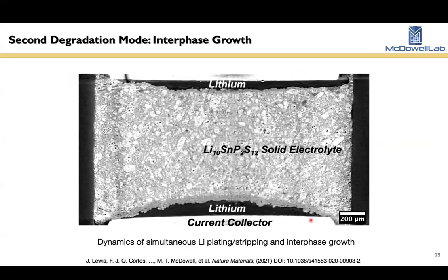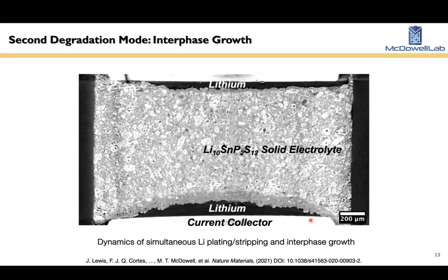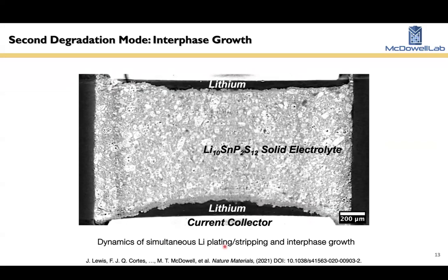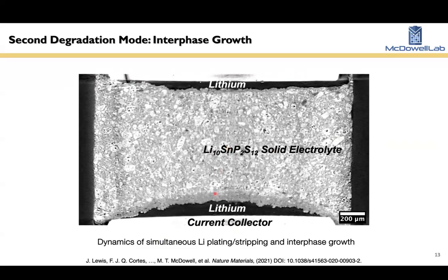There's another thing that I'll mention that's kind of related to this, and this is the formation of an interphase at solid state electrolyte interfaces. So if you're working in the battery area, you're probably familiar with this idea of a solid electrolyte interphase, SEI. This is a really important aspect of commercial lithium-ion batteries. There's an SEI that forms on the anode. It turns out something similar happens in solid state batteries. Various solid electrolyte materials, like the one shown here, have different stabilities in contact with lithium and other electrodes. And many of them are unstable at low potentials like that of lithium metal.